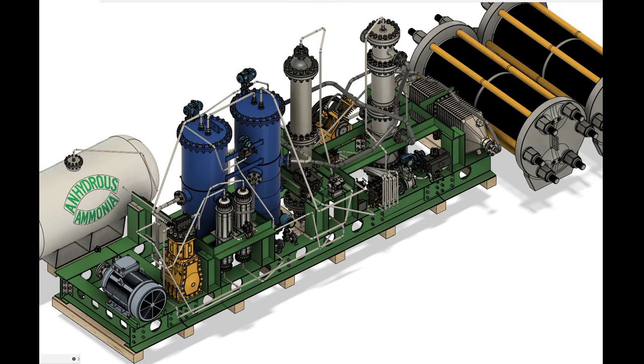In spite of this, there is a small chance that one such elemental combination may prove marginally more effective than iron. Only cobalt and molybdenum bimetallic nitrides could be possible contenders to replace iron. In 2001, Jens Nørskov predicted that cobalt and molybdenum bimetallic catalysts could attain high activity for ammonia synthesis, due to their excessively high and low nitrogen binding energies. Molybdenum binds nitrogen very strongly, while cobalt binds it very weakly. Combining the two proves to yield an effective catalyst in theory, but real-world tests demonstrate only marginal improvements, and most bimetallic nitride catalyst experiments experienced low stability and rapid deactivation.